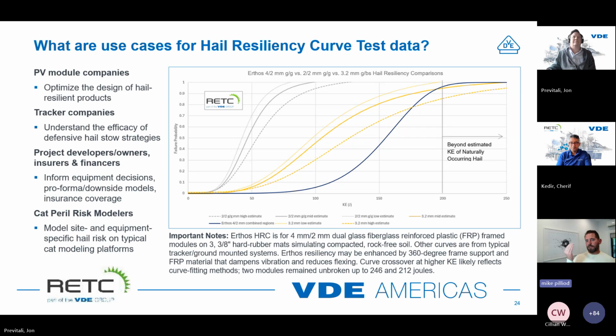It's okay in the glass world to do a staircase method, which means it didn't break at this height, you increase the height, same piece of glass, just keep going until it breaks. That's a very, very common thing in glass probability and durability to understand here in the hail resiliency. So there might be some concern like, oh, you just tested that piece of glass and it got weaker. That does not necessarily happen within a controlled environment within a lab. You can do this sort of staircase method, very common in glass testing. Yeah, Mike, that's actually really, really interesting. And that's really important to note.